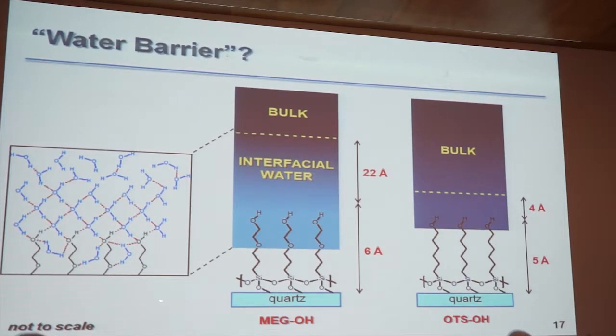In this case, it's quartz, but of course this applies to polymers, as I've mentioned, and indeed right now we're looking at things like stainless steel and other types of materials such as aluminum nitride that give you the same behavior. So hydration, and what water is doing in these extremely thin layers of 5-6 angstroms, is actually crucial to the world of biocompatibility. We've also carried out a number of molecular dynamics calculations of this system,